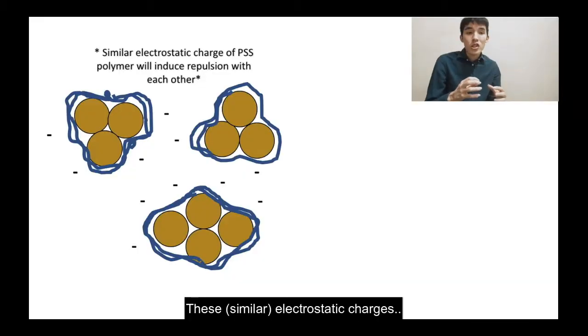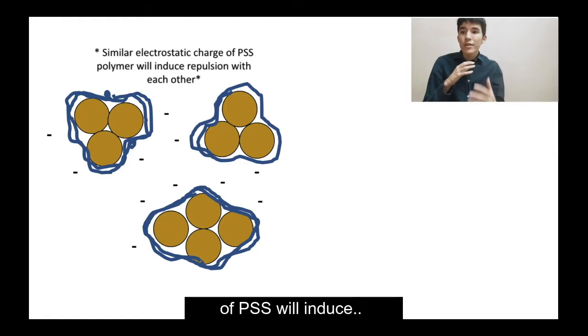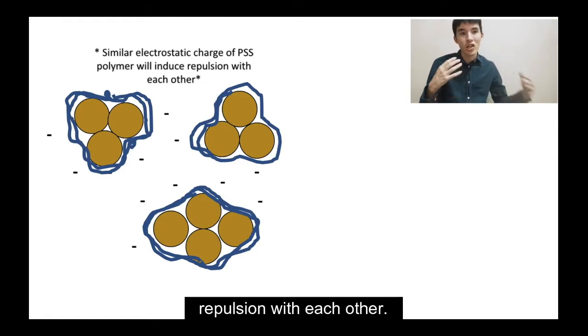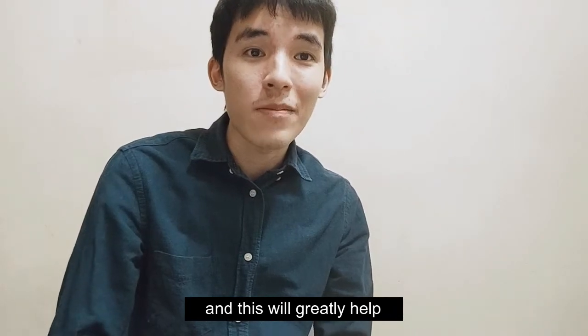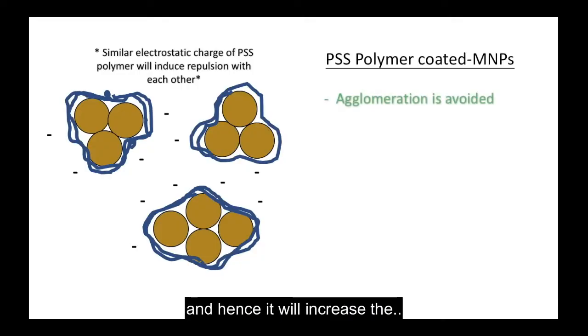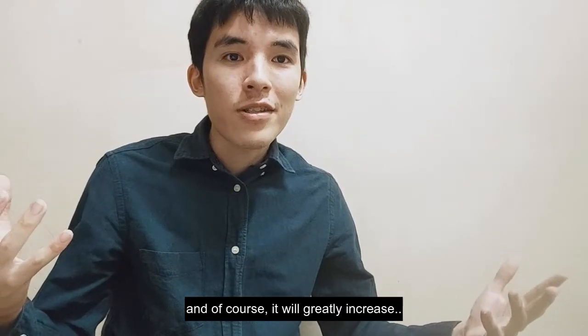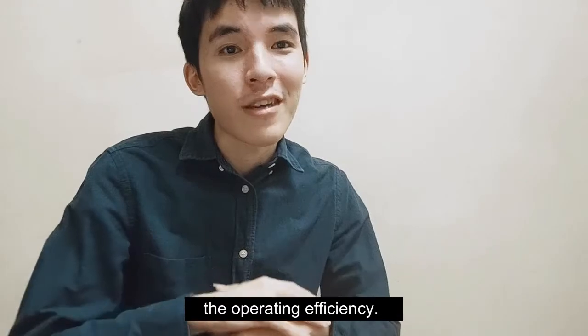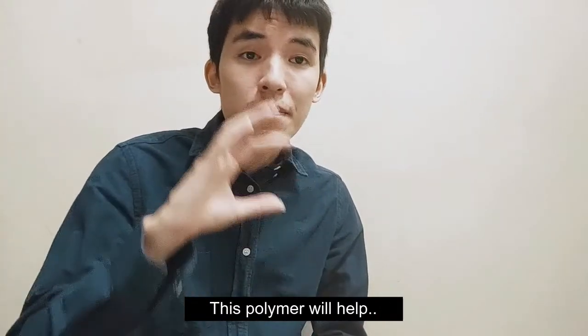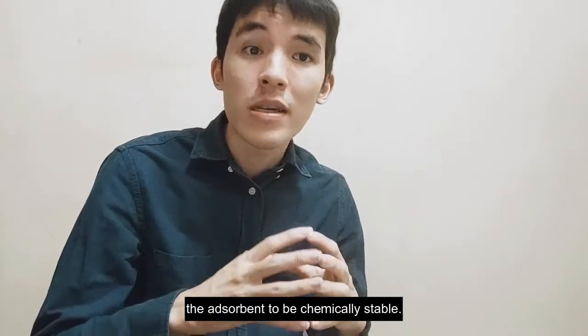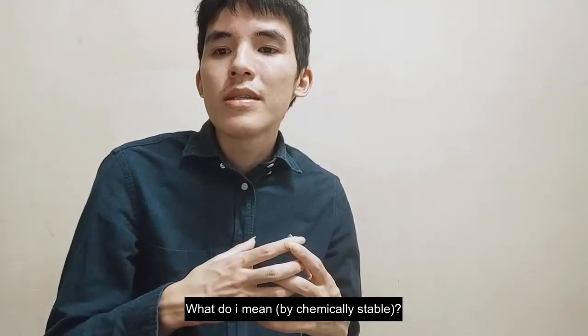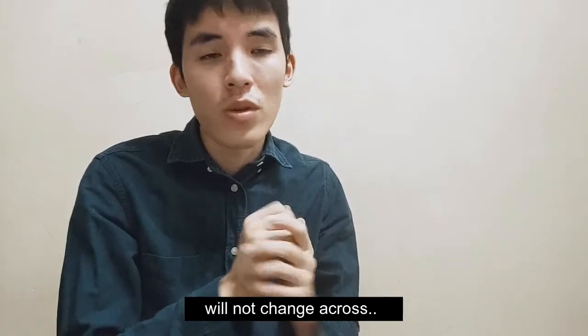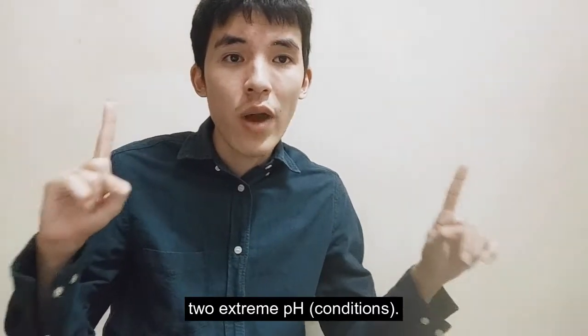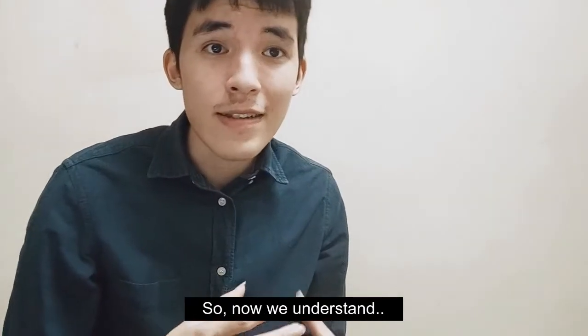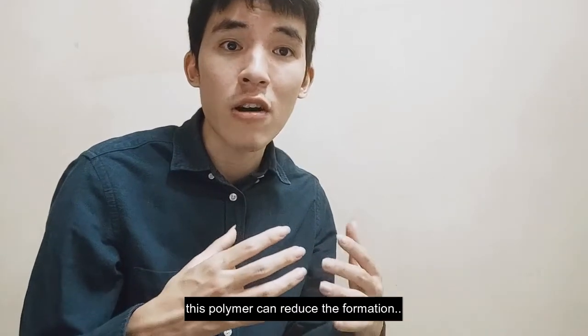The electrostatic charge of PSS will induce repulsion between the particles, and this will greatly help to reduce agglomerate formation, and hence it will increase the total surface area and overall surface energy, and of course, greatly increase the operating efficiency. There's one more highlight. This polymer will help the adsorbent to be chemically stable. What do I mean? Basically, its electrostatic charge will not change across two extreme pH values. So now we understand this polymer can reduce the formation of agglomerates.